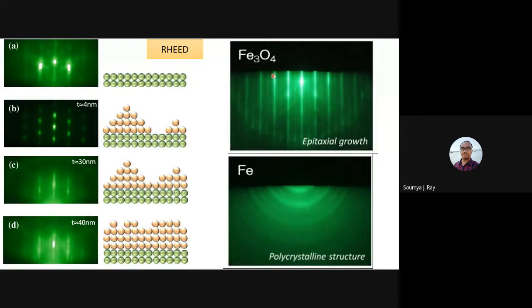Here you can see these streaky lines, and they are quite bright. Within each two consecutive bright lines, there is basically a dark spot. This kind of structure corresponds to an epitaxial growth. However, if we look at the bottom part, we don't see such bright lines. Rather, we see these semicircular lines. They typically correspond to a polycrystalline structure.